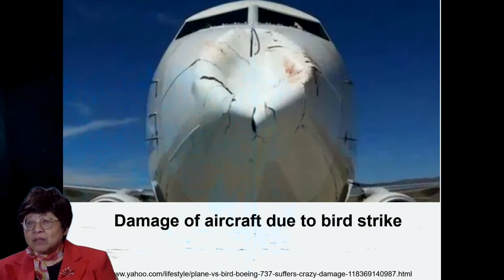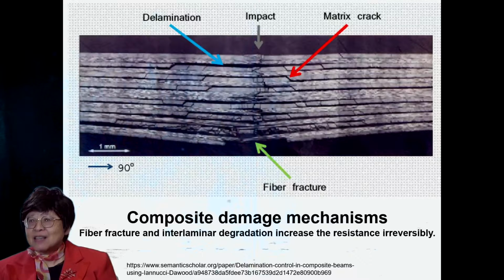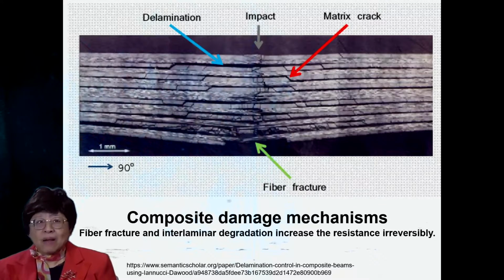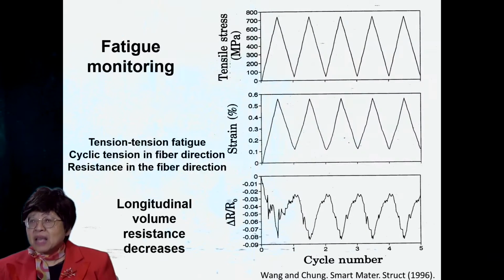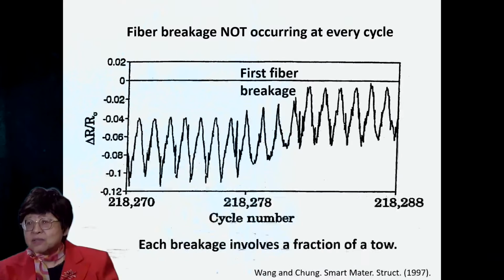Now, damage can occur in aircraft due to bird strike, for instance. And the damage can involve delamination as well as fiber breakage. And we can monitor the fatigue by subjecting the composite to tension-tension fatigue with the tension in the fiber direction and measuring the resistance in the same direction. So at the bottom is what I showed you before, but now I do it for many, many cycles.